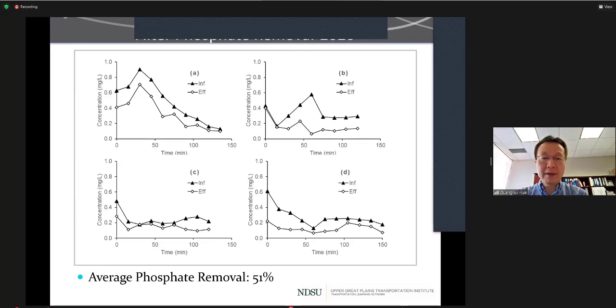So in addition to E. coli, we also monitored phosphate removal. Based on our past study, we know that steel chip and steel slag are very good materials for nutrient phosphate removal. And here we monitored the phosphate removal in 2020. We found that the average percentage removal was 51%. So we were able to achieve not only E. coli removal, but also we were able to remove phosphate. Therefore, this filter technology using steel chips and steel slag was able to remove multiple contaminants from the stormwater runoff.